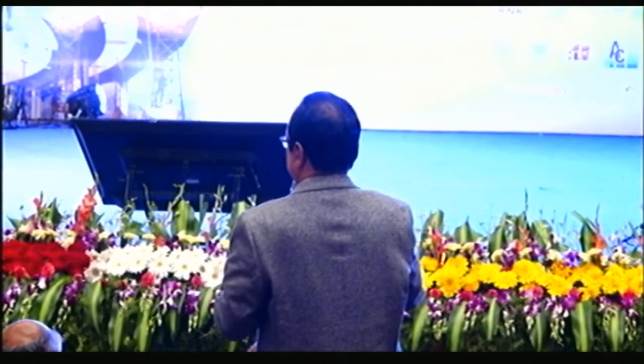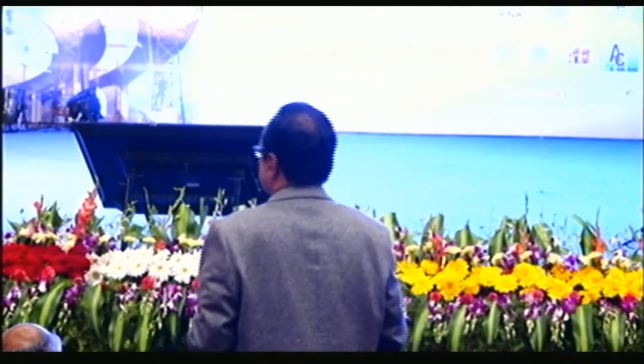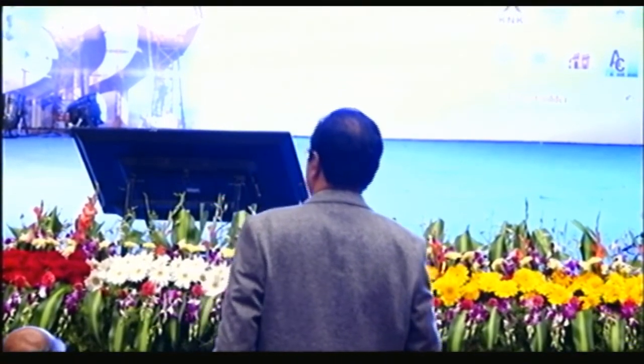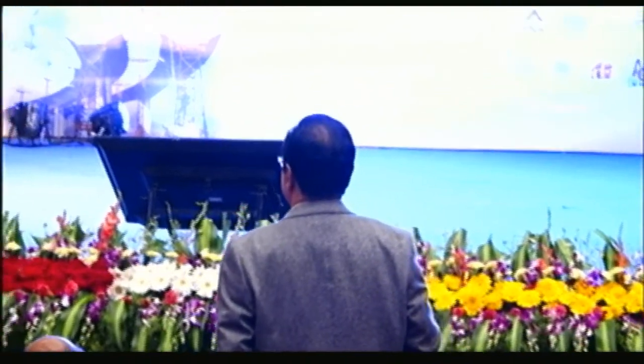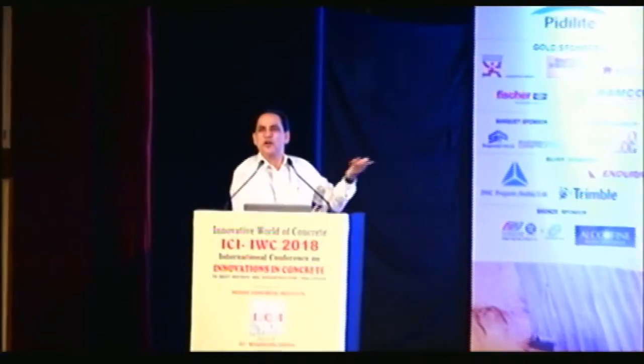The last slide you said that if the quality of concrete is poor, then the only way ahead is to go in for another layer. Yes, sir. Now, what should be the thickness of this layer? Because it is only a correction layer. Right, sir. If you are going for a bonded overlay, then I would recommend that it should not be less than 100 mm. If it is unbonded, then it has to be designed like a new normal concrete. Then it may be around 250 or 300 mm. But for bonded overlay, we are preparing a code also. It is under preparation these days, and within the next 1 or 2 months, you may have a bonded overlay code also. In that, it has been mentioned that minimum should be 100 mm. In bonding conditions, M40 grade is same.